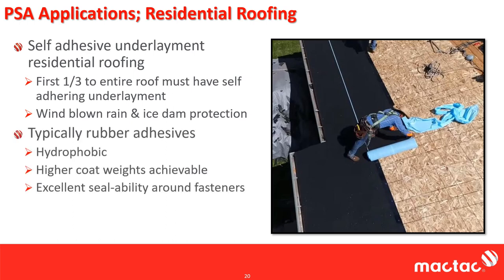These adhesives are traditionally rubber-based adhesives. They're hydrophobic, which means they repel water. This also prevents capillary action from allowing water to seep underneath the shingle and the membrane itself. Rubber-based adhesives can be coated at much higher thicknesses. This allows for better adhesion to the MDO board underneath, as well as sealability around the nail that's been driven through the membrane from the shingles above. There's also a lot more self-adhesive shingles being sold. However, these are primarily used for repair right now and not new roof installations.